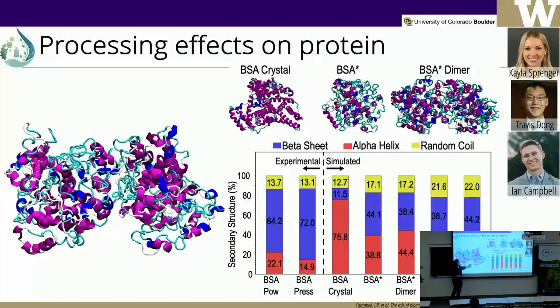Here they start from a dimer of our protein. This is BSA protein that they are modeling. And these are the FTIR results that we took, experimental results, of the powder and then a pressed material. So this is a self-bonded material, and you can see that our hot pressing does change the alpha and beta conformations, as well as the random coil, well, not really random coil, but the alpha and beta ratios. Even in pure protein, pure BSA, we do see a change. And then you see a bunch of different columns over here.